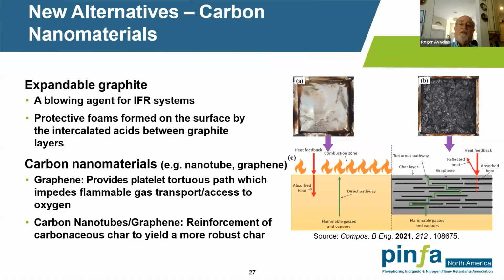Typically, you're going to be using it with a non-halogen flame retardant. I've seen it used a lot with silicones as well as with borates to reinforce that glassy char. Carbon nanotubes as well, and in combination many times with graphene, again as a reinforcement of the char to give you a more robust char.